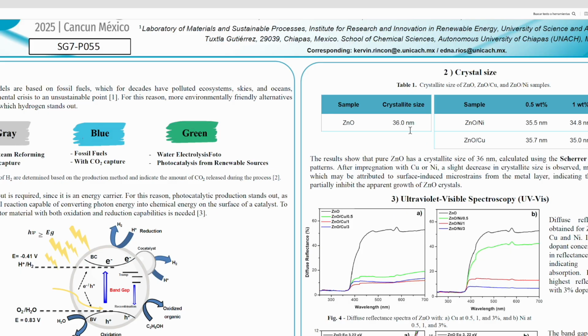All right, let's move on to the part where we calculate the crystallite sizes using those diffractograms, which are shown here in table 1. In this table, we can see that the crystal size of the zinc oxide was calculated using the Scherrer equation, in which we use the average peak width, the incidence angle, and so on. We observed that a crystallite size of approximately 36.0 nanometers was successfully obtained.